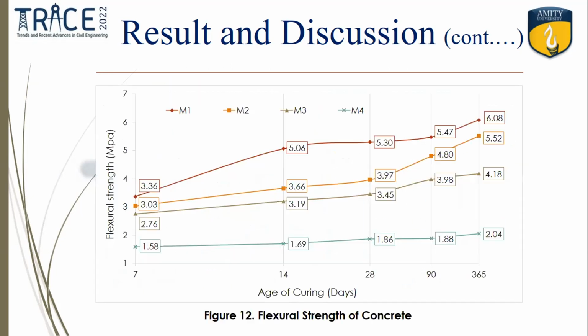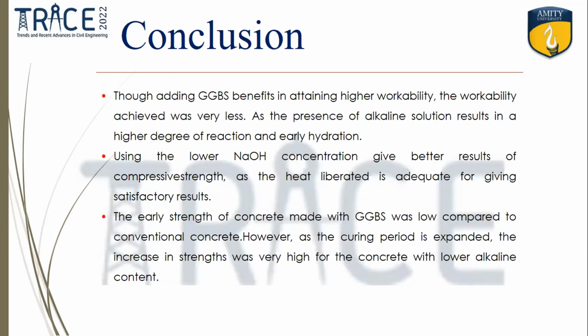Yeah, sure. These were the results. So I'll quickly jump to the conclusions. As the concentration of NaOH mixed with GGBS increases, the workability reduces. If I'm mixing M10, the workability is a bit reduced. If I'm mixing, say, 15 mole concentration, the workability is more reduced. As I went on increasing the molarity, the workability reduces. So it accidentally became a rapid hardening concrete.